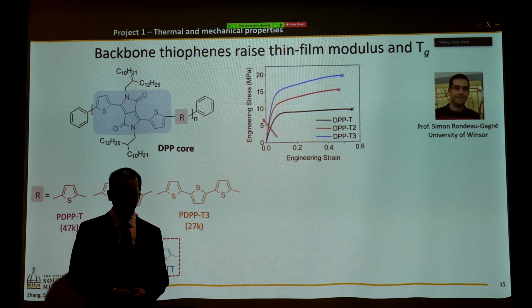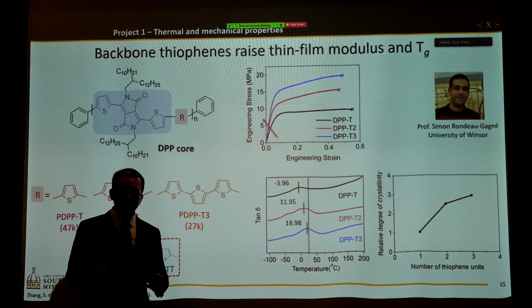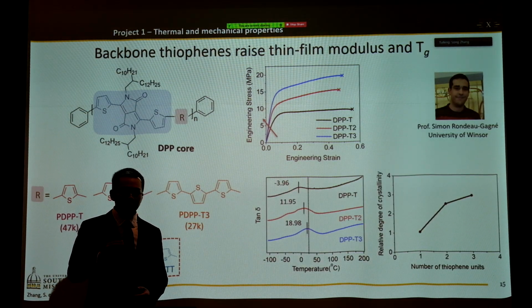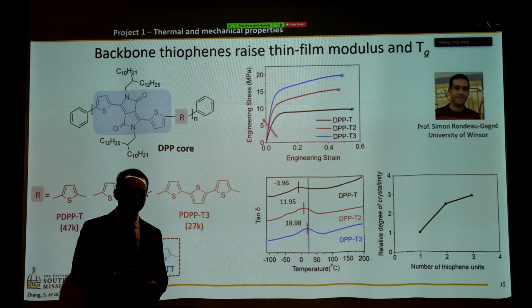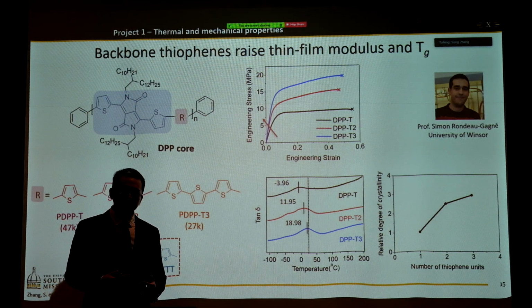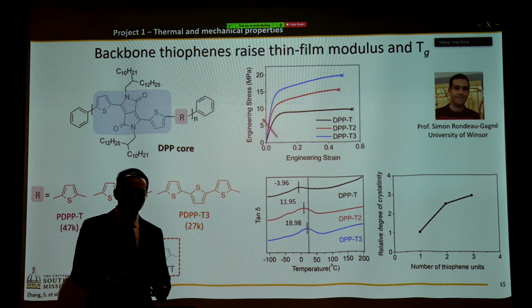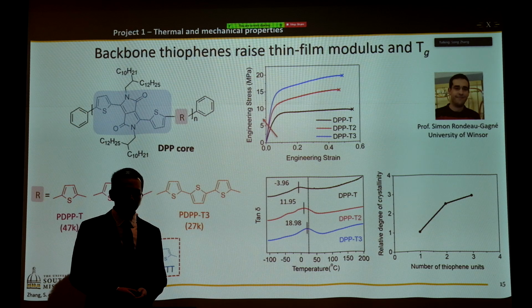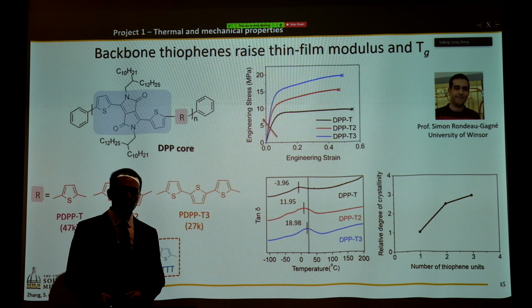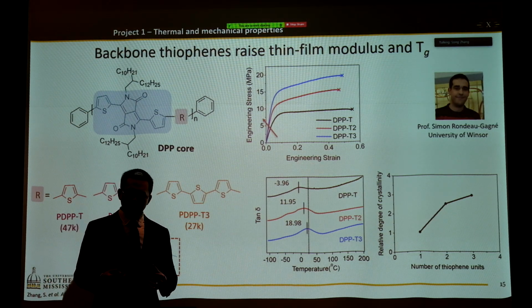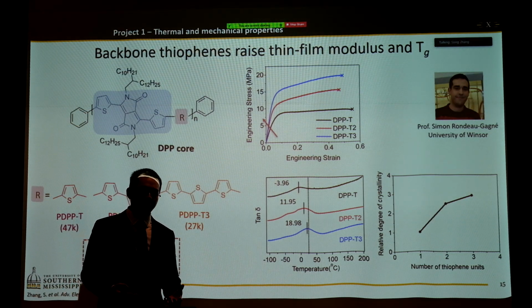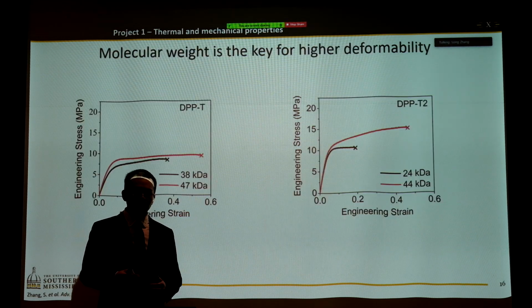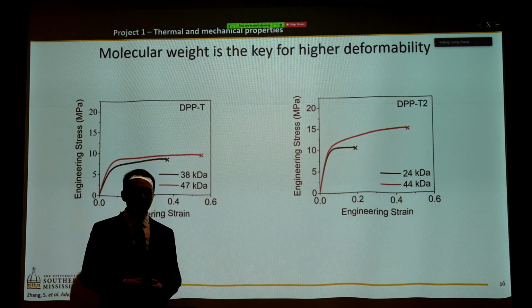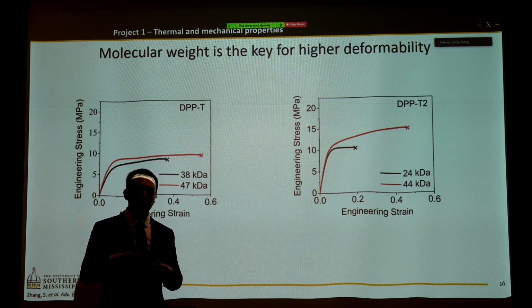of more thiophene structure. And later, the increase in elastic modulus was explained by increased glass transition and increased degree of crystallinity. However, we still do not know why the glass transition is increased if the backbone is becoming less rigid. And the second observation we made from the stress-strain curve here is the crack onset strain. It turns out the crack onset strain can always achieve like 40%, and it does not seem to be affected by the polymer structure itself. So we engineered polymers with different molecular weight and found it might be the key for higher deformability.